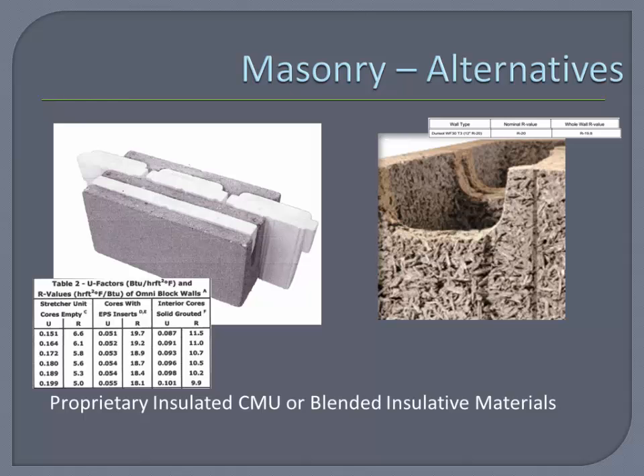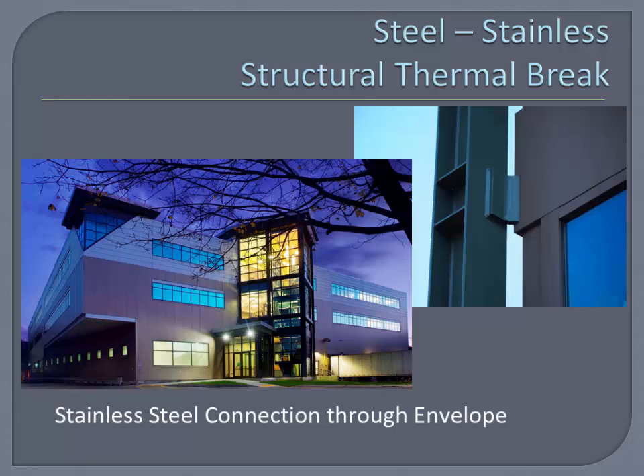What are the other alternatives? Well, there's proprietary block out there that's insulated. This is Omni block on the left. May or may not be used up at Spruce Peak on a small project. And this is an agricultural-based cement fiber block on the right. So then another strategy to mitigate thermal breaks is stainless steel in lieu of carbon steel. Stainless is about 1/3 less conductive, pretty straightforward calculation there.